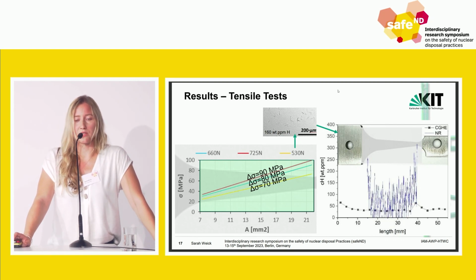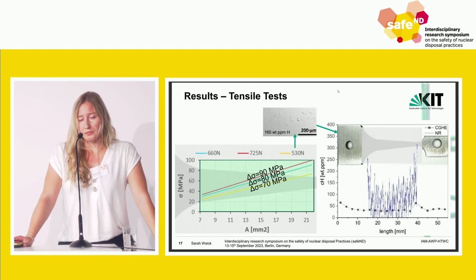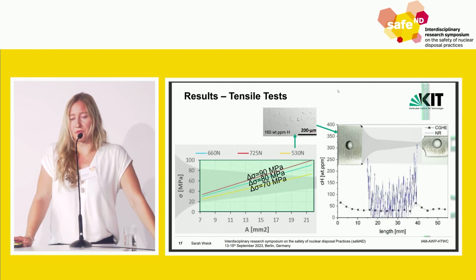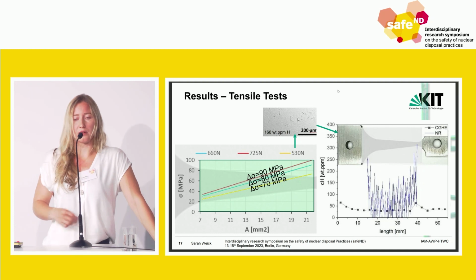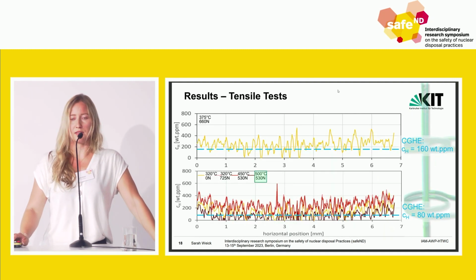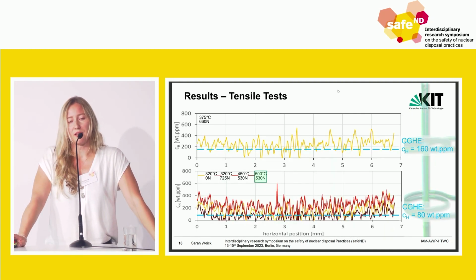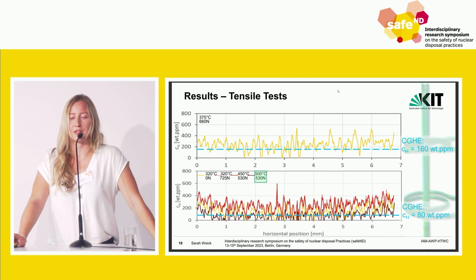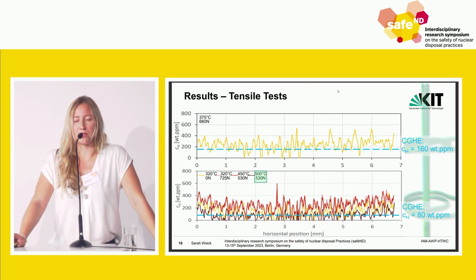We tested this with several pressure conditions at different temperatures, always trying to stay in the elastic range. We couldn't see any influence so far, which is also due to the fact that we had quite a long time to install our facility first at the beamline, so the time for experiments was quite short.